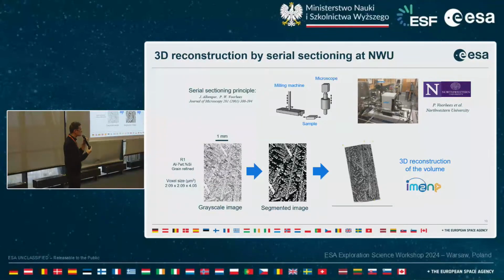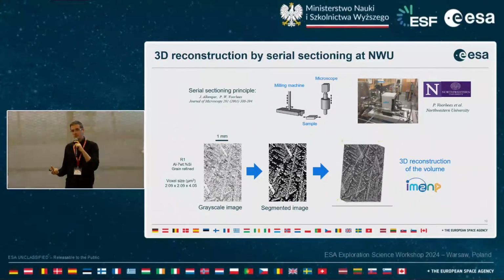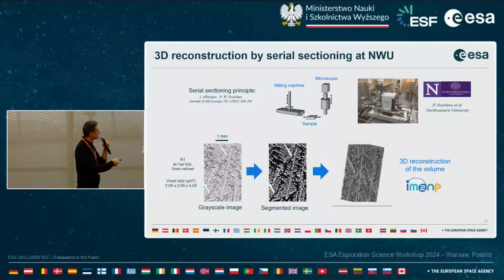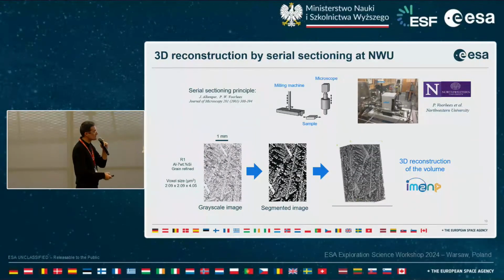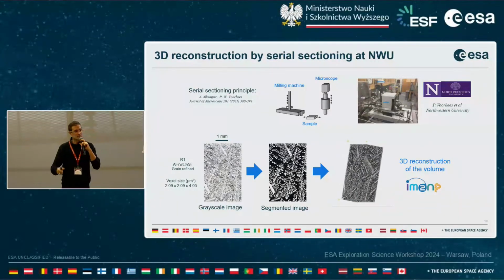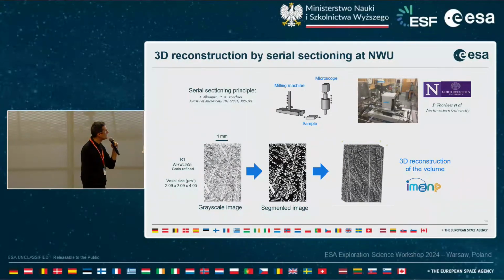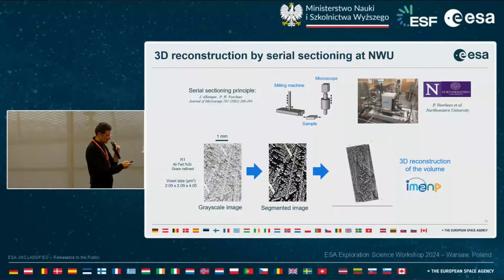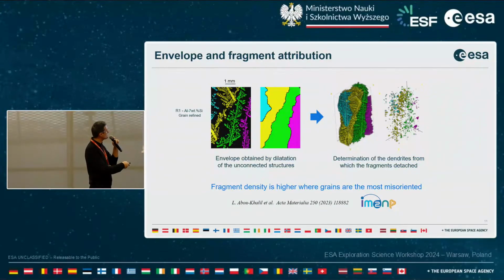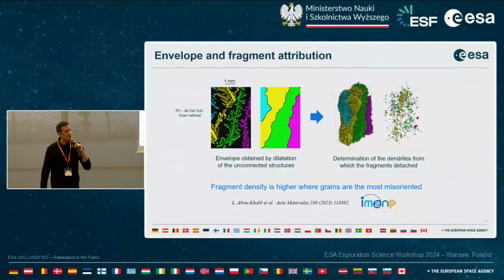So it's destructive, so we lose our sample, but we get nice images with a very good spatial resolution and size of the reconstruction. And what did we do from that? Well, here you can see more detail about this work in a recently published paper. But here, one of the main results was that it was possible